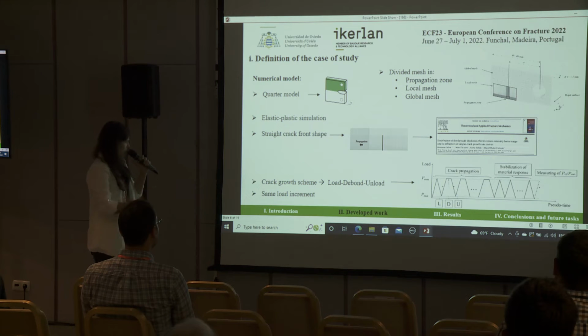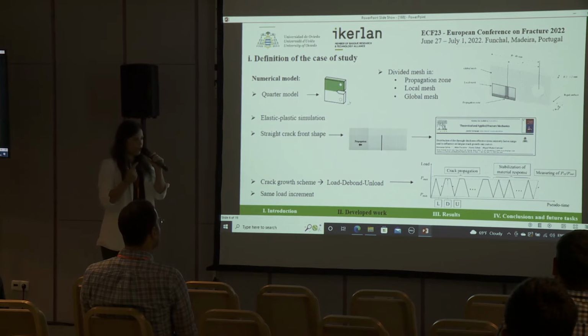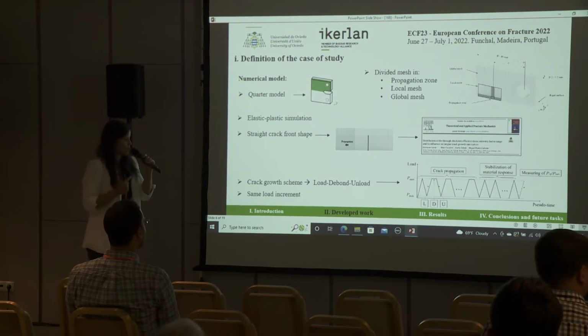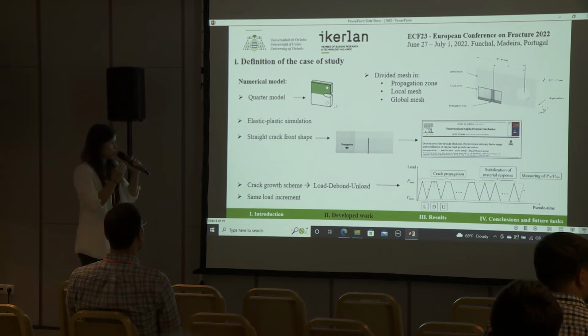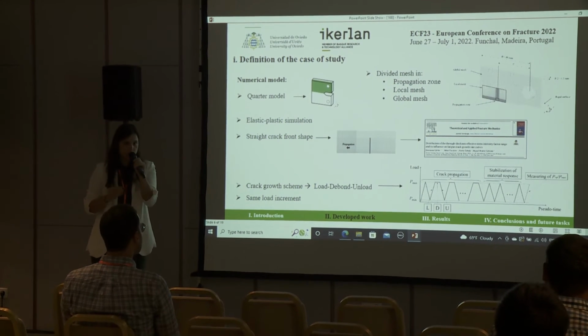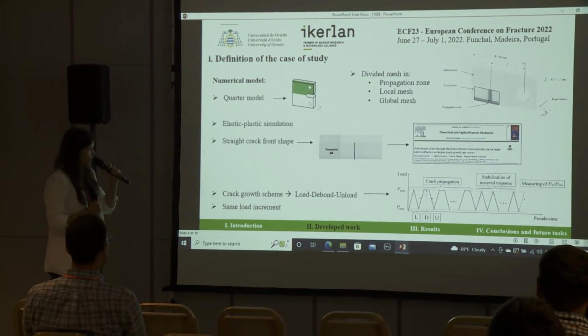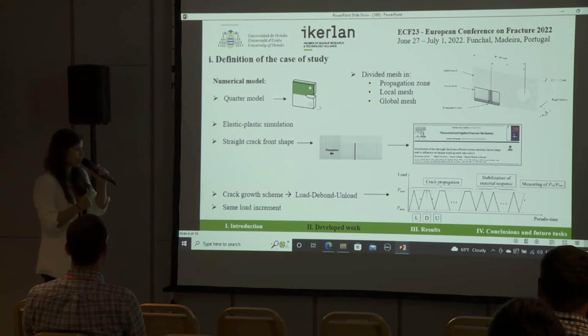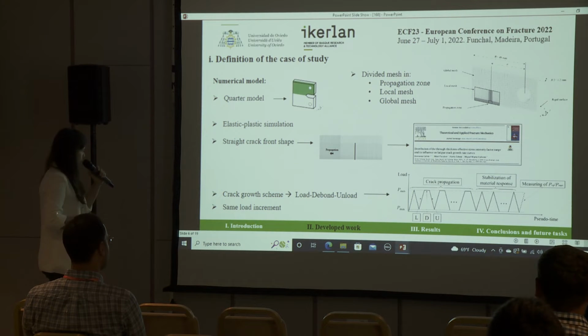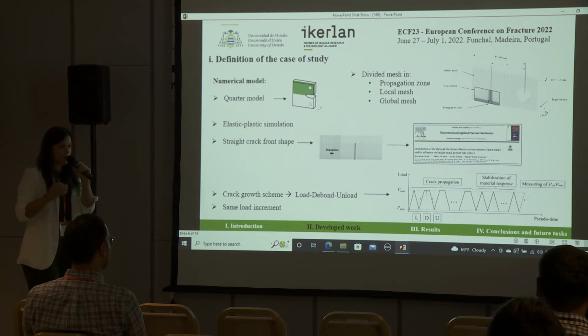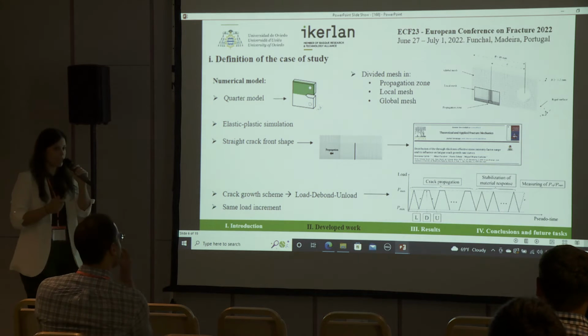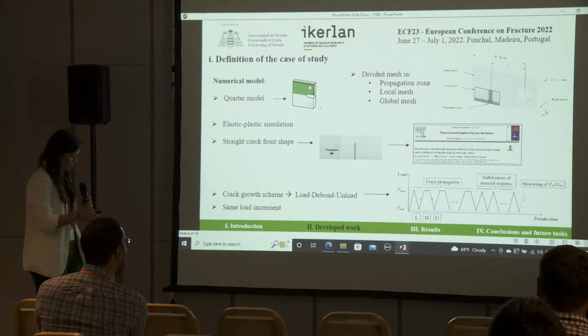And finally, here you can see the crack growth scheme, which is composed of one debond cycle, 20 load and unload cycles, considering the node releases for the crack propagation, and 8 cycles to stabilize the material response. And finally, the same load increment was used to measure the P_open or crack closure.